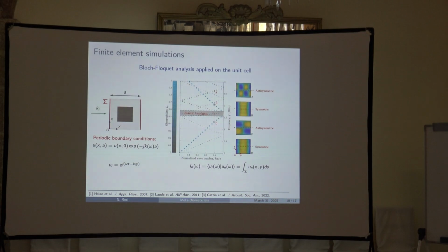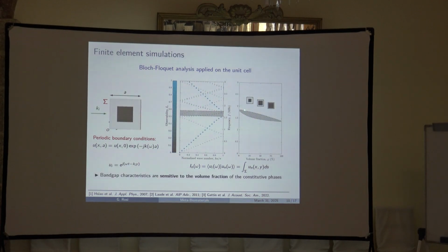So once we identified this bandgap, this zone that we want to use, we did the analysis for different sizes, and you can see that the bandgap shifts in position and in width. So this is encouraging, meaning we change something that is supposed to be correlated to the biomechanical behavior, and the bandgap evolves. And this is the diagram of the bandgap as a function of the volume fraction. So again, the objective is not to optimize the bandgap to dump something, it's just to see that we have some kind of sensibility, so the slope is not zero, and that we can expect the bandgap to follow the volume fraction.